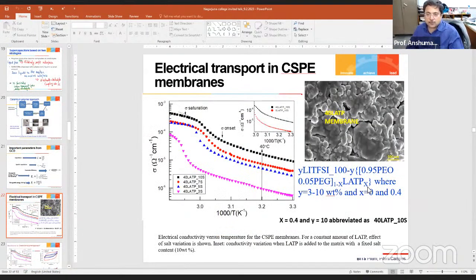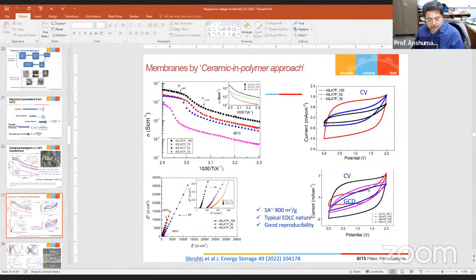So now I'll go quickly. Electrolyte characterization, all of you are familiar. You make the film, then see the electrical conductivity, try to see at what temperature it reaches a high conductivity. And after that, you work at that temperature. No harm in going to slightly higher temperatures. We were actually working at a little above 40 degrees initially, but now we have developed some others which are being used even at -10 degrees also.